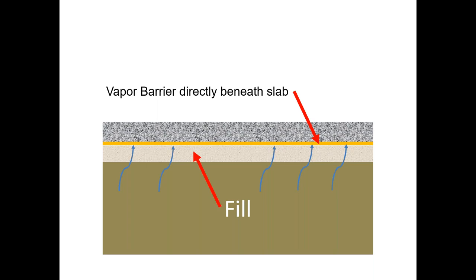Otherwise, you can put down things like breathable sealers and that kind of stuff. Like, you could put an acrylic sealer down there. I wouldn't want to put a colored one, but a clear acrylic sealer will breathe. We put clear acrylic sealers down over concrete that's just been poured hours ago, and they don't get pushed off by the moisture. So you could seal that with an acrylic sealer, but it might slow that rate down a little bit, but it's a difficult problem to address if you've got it.